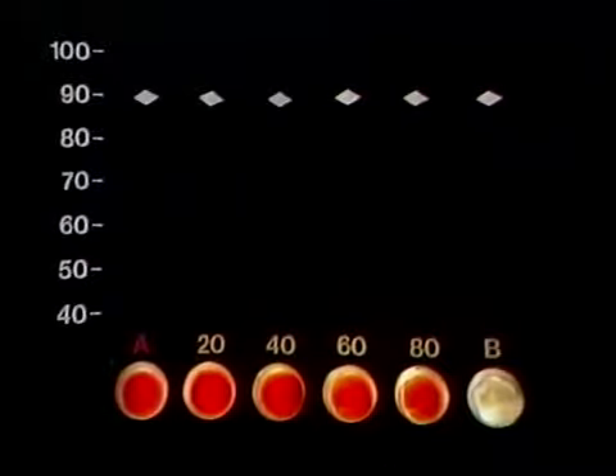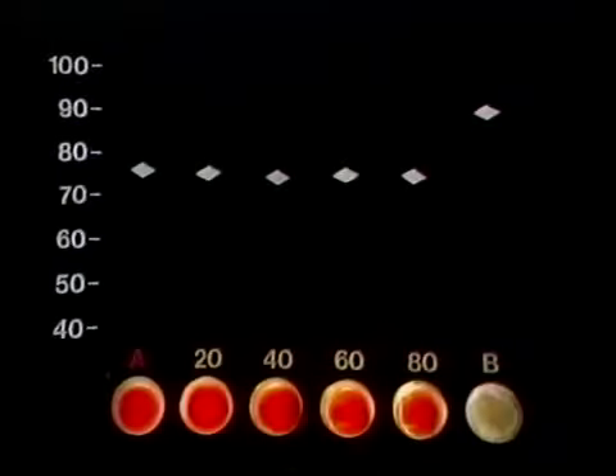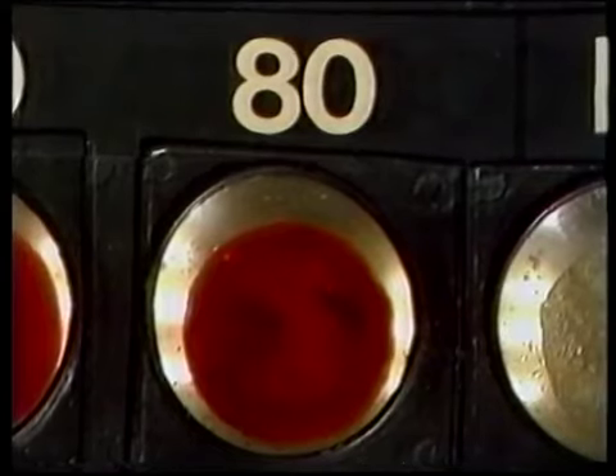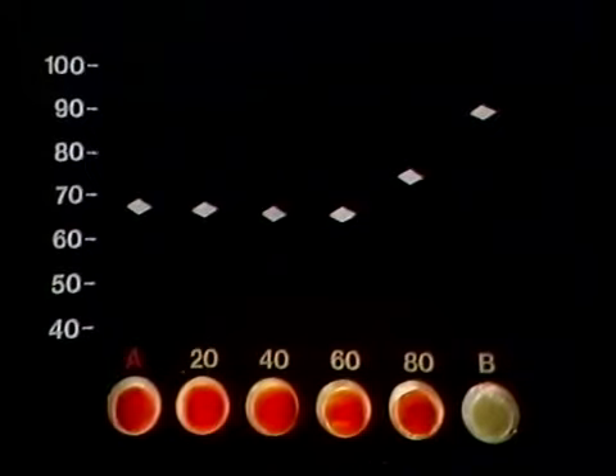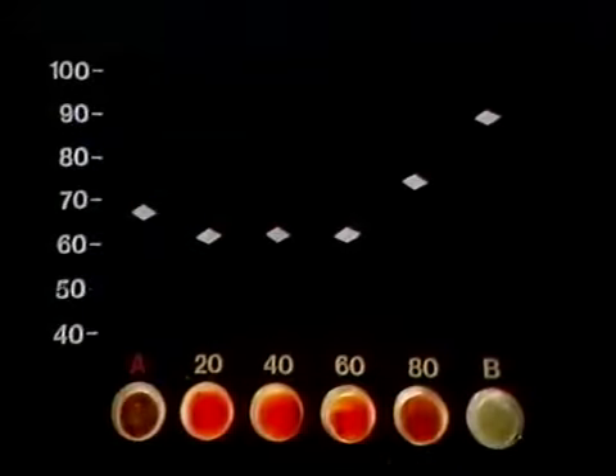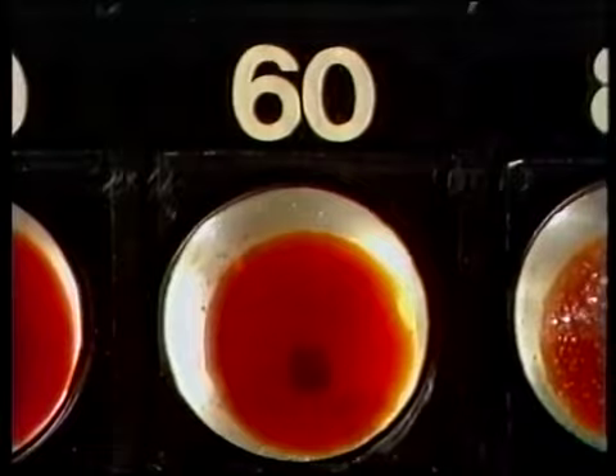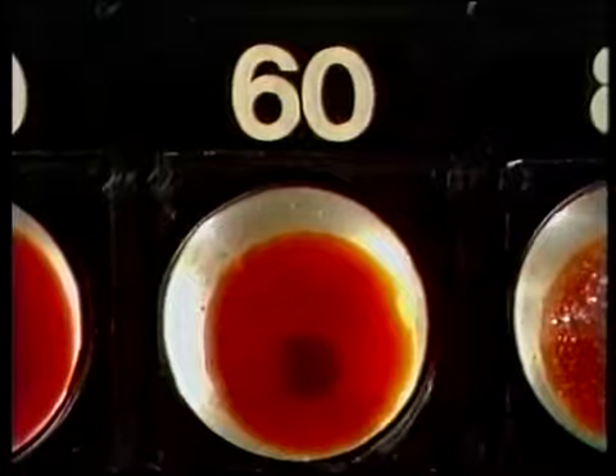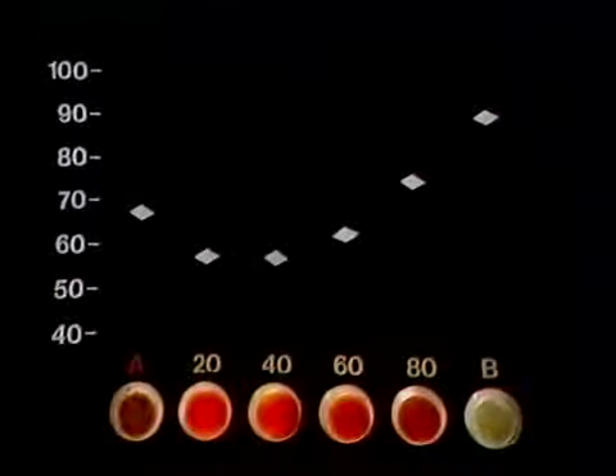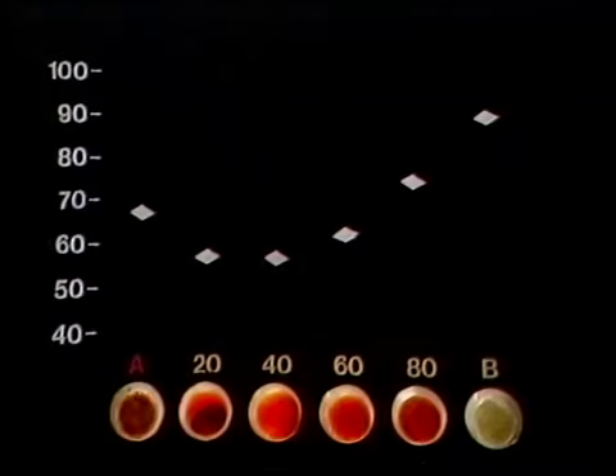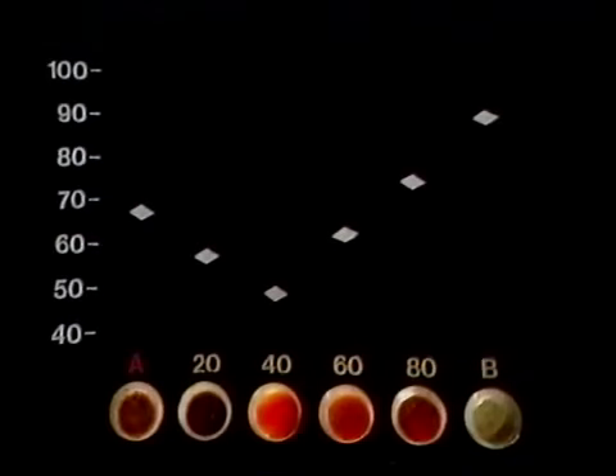The temperature is just 89 degrees centigrade, and something's happening in the dish containing pure B. It's difficult to see, but in the 80% B melt, there are now some crystals, and the temperature is 77 degrees centigrade. Now we're at 67 degrees centigrade. That's the crystallizing temperature of pure A, and it's turning solid. Now at 62 degrees centigrade, 60% B is crystallizing. Now 20% B at 57 degrees centigrade. And finally, at just under 50 degrees centigrade, 40% B.